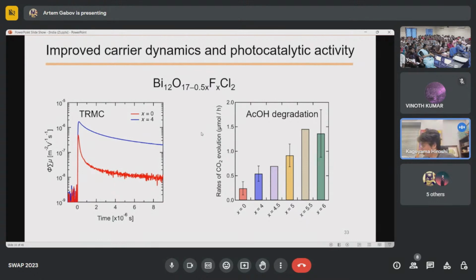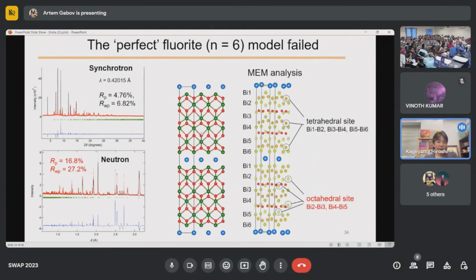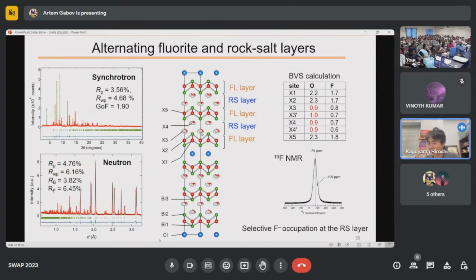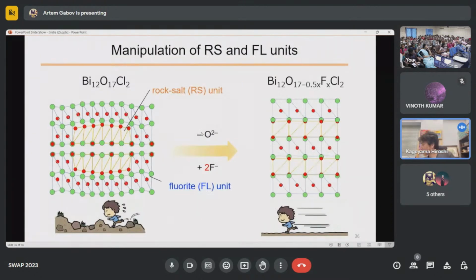But the remaining problem is the Rietveld refinement. We did synchrotron diffraction and neutron diffraction. The synchrotron diffraction seems to be okay, but the neutron diffraction has large deviations from the expected modeled perfect fluorite layers. So something is going on. Then finally, we found that our expected structure is not correct. So this is the final structure.